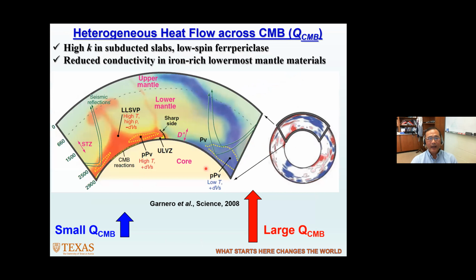So if we take that into consideration, it's conceivable that all those effects that we observe because of the spin transition, because of the amount of iron, as well as the changes in the mineralogy, can actually affect thermal conductivity in the lowermost mantle.